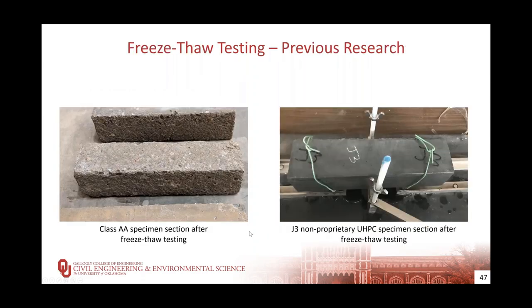Here are two specimens from previous research looking at a class A, class AA, and J3 specimen. After testing, you can see just how pocketed the class AA specimen became, where it appears the J3 specimen is unaffected by the testing. This is also noteworthy, as the J3 mix was not even air entrained.